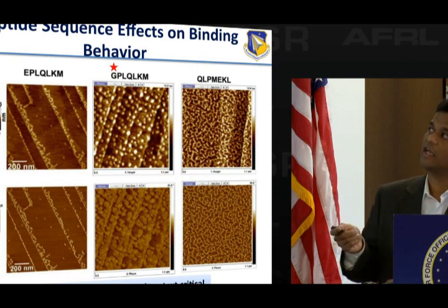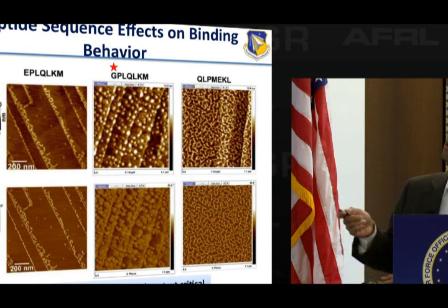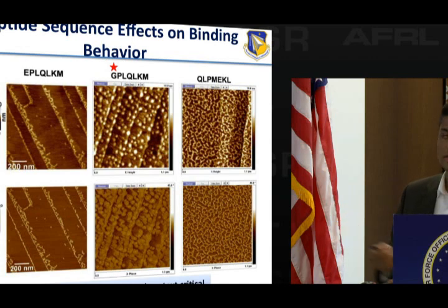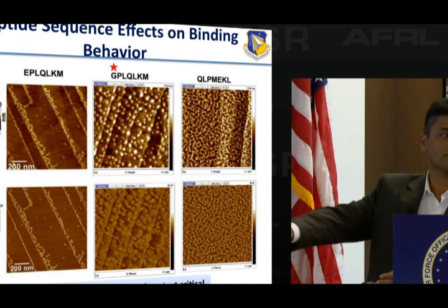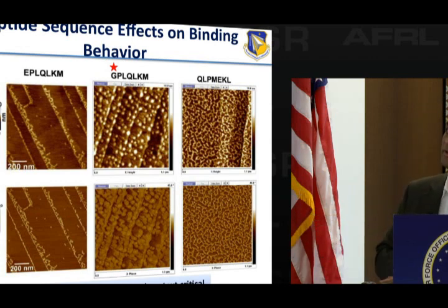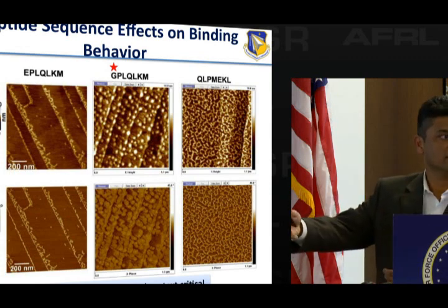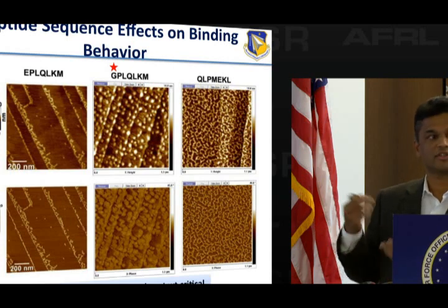But now if I say, okay, is it just one amino acid? Now what if I took that whole sequence and I jumbled it? What happens? So I take that same sequence, I just jumbled it, and create a synthetic peptide. Now you can see the morphology is completely different. It coats the whole surface and forms this sort of reticular network as seen by AFM. Okay, so this tells you two things. One, that amino acid composition is critical, but also the context on how that amino acid is displayed is also critical.